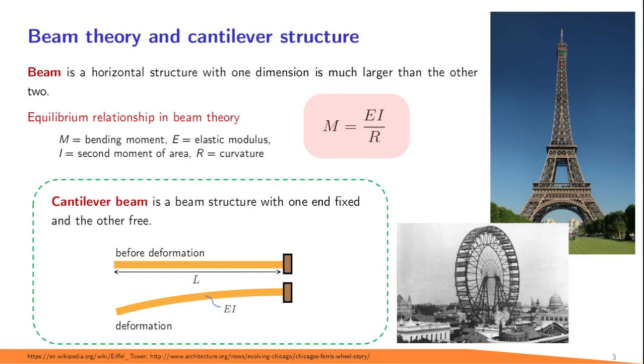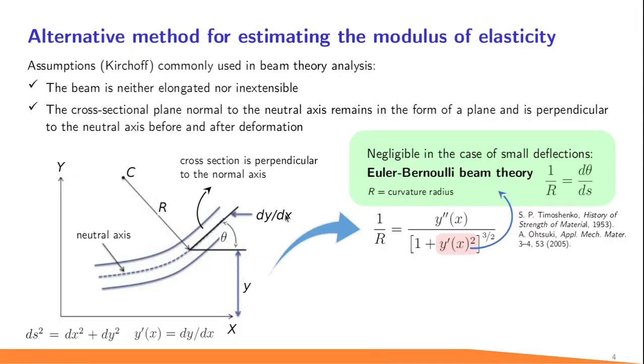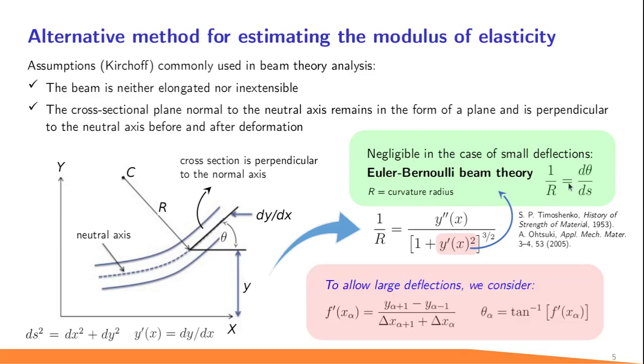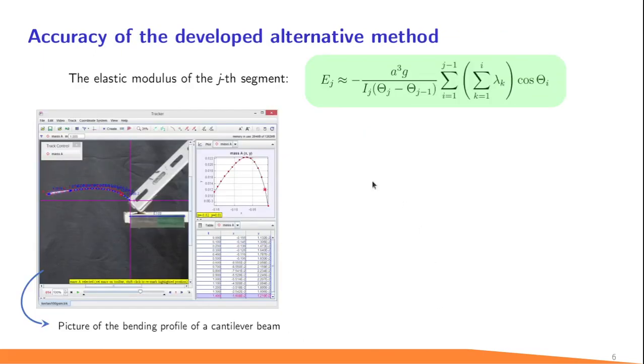And for our purpose, we discretized this relationship. We first transformed the bending equilibrium equation into discrete form, and since we would face arbitrary bending angles, either small or large, the Euler-Bernoulli equation shouldn't be applied, since this equation has been derived under the assumption of small bending angles. To allow large deflections, we consider Taylor expansion. Therefore, the elastic modulus of the j-th segment of the discretized bending beam can be measured with the following equation, and we examine several samples to determine the elastic modulus.